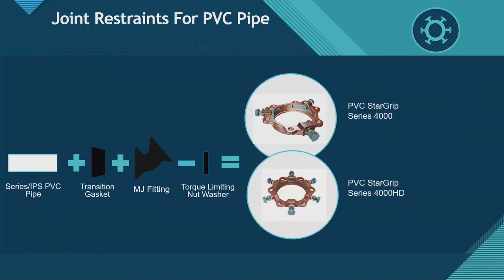And make sure it's not removed for C900 pipe, up to 12 inch. Above 12 inch, we don't recommend it be used on IPS or series pipe. And forgot to mention, for the ductile iron ones, can be used on steel pipe up to about 12 inch, Schedule 40, Schedule 80. Above 12 inch, call the joint restraint manufacturer. It can be used on steel pipe above 12 inch if it's cast iron OD steel pipe. Wall thickness is thick enough as well.